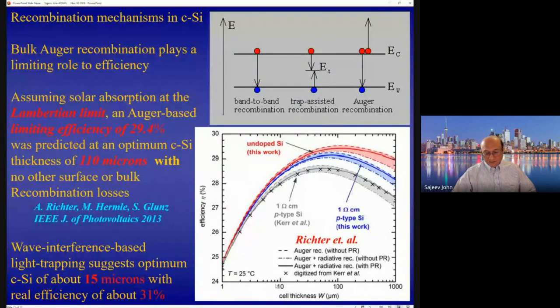So as you make the solar cell thicker, you can certainly absorb more light. That's good. But as you make the solar cell thicker, you also create more recombination effects, especially Auger recombination. So there's a trade-off between these two effects. And if you focus on the red curve at the top, it suggests, that this is their calculation, that the actual optimum thickness of a silicon solar cell would be at about 110 microns in thickness, and that the maximum possible efficiency, the limiting efficiency, would be around 29%, assuming Lambertian light trapping.